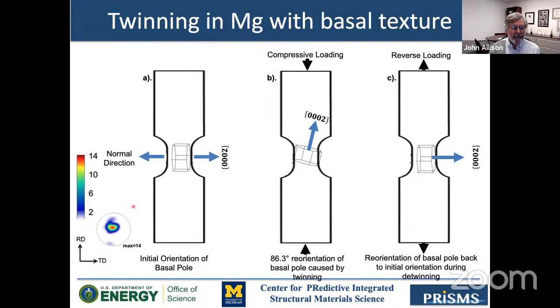Now, because these materials have so much anisotropy, the deformation modes are very dependent on the texture. Very frequently in pure magnesium, as well as magnesium aluminum and a lot of the conventional alloys, we get a basal texture either during rolling or extrusion. Most of our results are on extruded material, where this would be the extrusion direction and then the radial direction. And so we see this very pronounced basal texture.